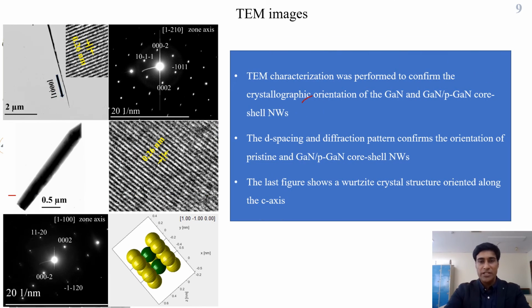And these are the TEM images. The TEM characterization was performed to confirm the crystallographic orientation of the pristine GaN and GaN/p-GaN coaxial nanowires. You can see the lattice d-spacing. The d-spacing is around 0.26 nanometer, which is attributed to the c-axis orientation.